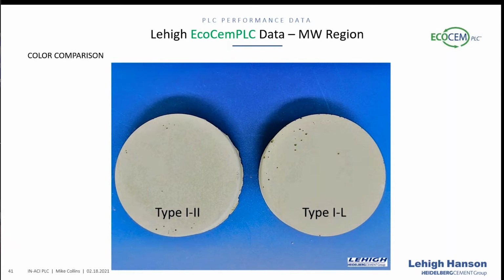And again, that's because it has more of the whiter limestone included in it. But powder is not the end game for us. It's where does this end in concrete? So what we did, our color lab at Speed took 3 parts silica sand and blended that with our Portland Limestone Cement and the type 1-2 and made a mortar. And then they were able to shake the air out of those and took some pictures. And I guess the proof's in the picture because it's really hard for me to tell the difference between those 2 pucks. Very similar color.